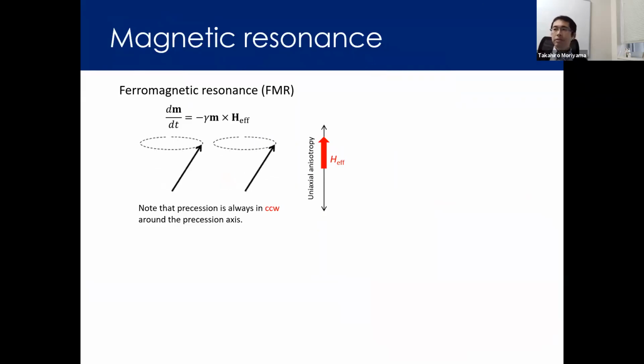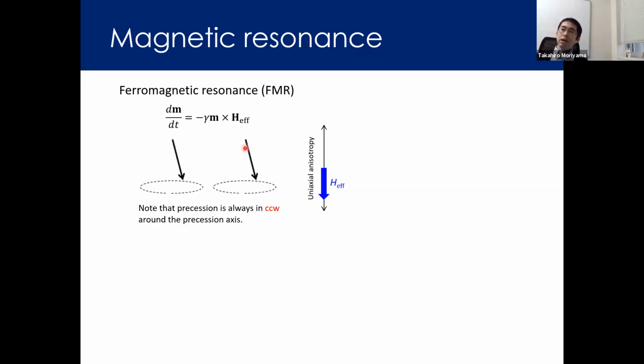First, I'd like to briefly explain what the antiferromagnetic dynamics is. So we start from the usual magnetization dynamics in ferromagnet, shown here. We all know that on resonance, the ferromagnetic moment precesses around the effective magnetic field. This equation of motion is basically described like this. Here we should note that the magnetic moments always precess counterclockwise with respect to the effective field direction. If you flip the magnetic moment in the other direction by applying the external field or some other technique, you see the counterclockwise precession with respect to the effective field still remains.